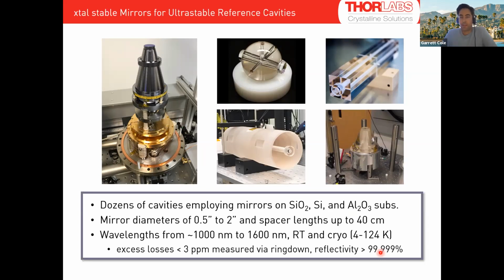As I mentioned, we can get the absorption and scatter down to the less than 3 parts per million level in a good run, which means we can achieve reflectivities well in excess of 99.999%. So, linear cavities with finesse at the 300, 400, 500,000 in our optimized systems. I'm not going to go into more detail. I already went into a lot of detail on this, but these systems are phenomenal.